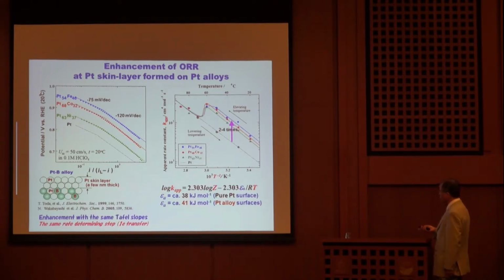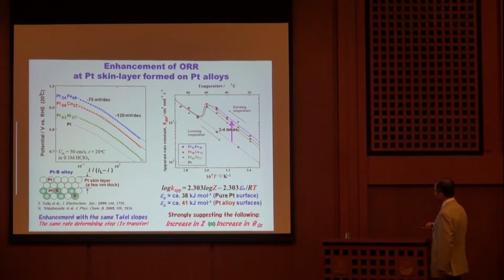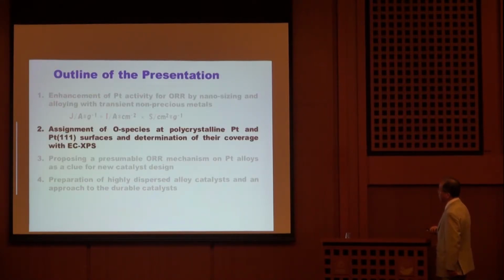So we expect such a Z value increase strongly suggests an increase in oxygen coverage on the surface, which relates to the oxygen reduction reaction. So we now intend to try the assignment of the oxygen species at platinum, polycrystalline platinum, and also the single crystal surface, and the determination of the oxygen coverage.